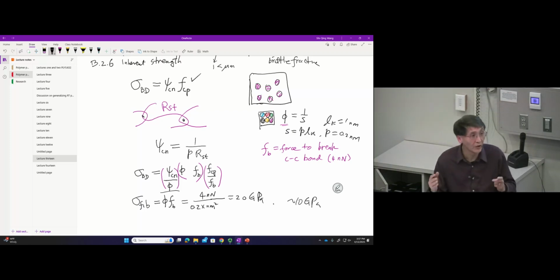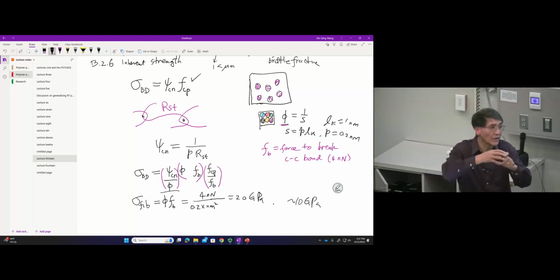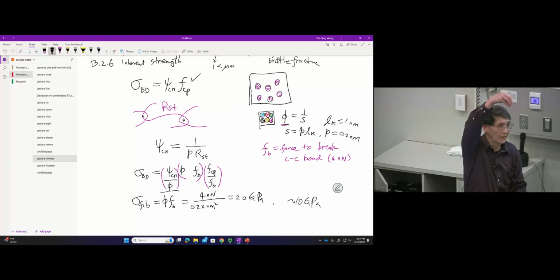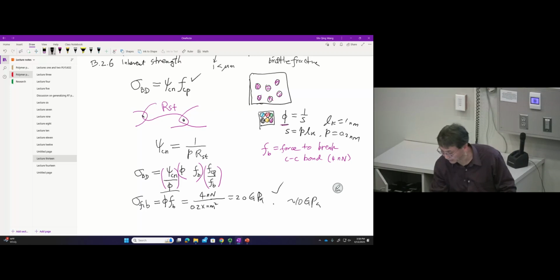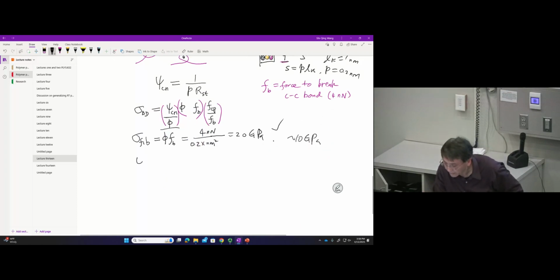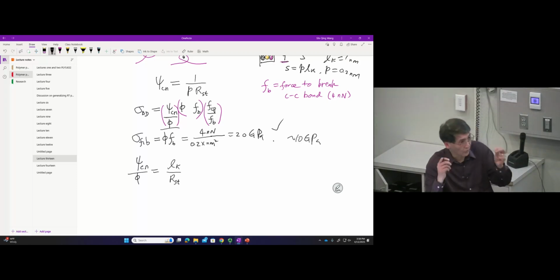this ratio. It's a ratio of 2 area densities. Remember, phi is the ideal limit. That's as dense as you can pack the chain, right? Each chain just occupies its cross-section once, and it starts to bear load. That's the most impressive theoretical limit you can get. And let's look at this ratio. What is this ratio? Well, by definition, it's a ratio. I'm just plugging in Kuhn length divided by R, the size of the strand.